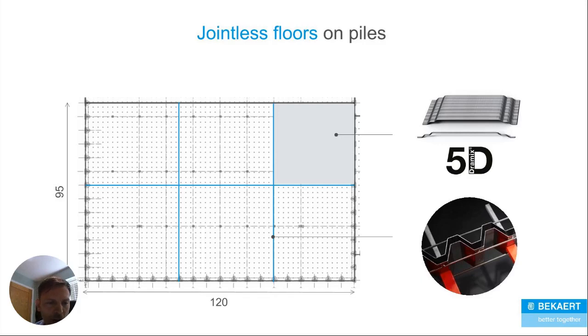Here we see a diagram of a floor of around 11,000 square meters, so 120 by 95. You can see that the daily panels are split up by the use of a leave-in-place joint. That one that you see there is called Signature, which is similar to the Alpha joint that I explained earlier. We have panel sizes there of around 40 by 40. So call it 1,600 square meters per day. So that 11,000 square meter floor will be poured in 6 days.